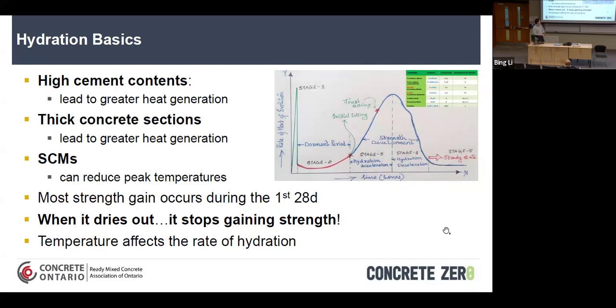Anything here I really want to show you? Heat hydration time. The real kick for heat hydration happens after initial set. Initial set is defined, when you do a penetrometer test, as 500 PSI. So when you get 500 PSI, you hit initial set. Final set is defined as 4,000 PSI on that penetrometer test. Okay, so that's the strength that gives you those initial and final sets. And you'll see that when it hits initial set, that's when it starts to skyrocket in hydration. When it hits final set, that's when it starts to calm down and slow the heat of hydration down until it gets to a steady state.